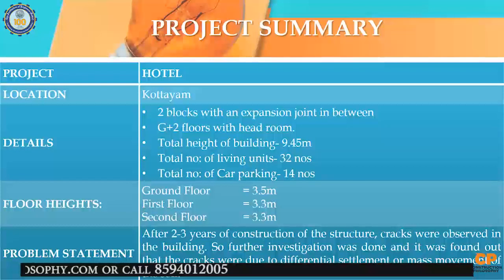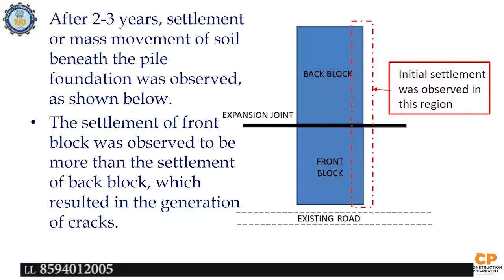Further investigation was done and it was found that the cracks were due to settlement or mass movement of the soil, because this particular property had an empty plot in the neighboring area. Here you can see the mass movement of the soil beneath the pile foundation, as shown below. The settlement of the front block was observed to be more than the settlement of the back block, which resulted in the generation of cracks. Here we found that the material was moving from this side to the plot, which was at a lower level, and the topsoil comprises very soft clay, going into a bit of laterite strata and then into the rock.